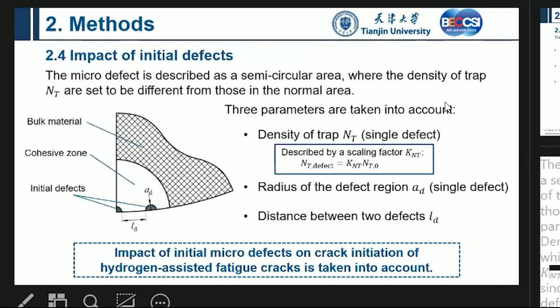I would like to introduce some defects because, for example, the material is not normal. So micro defects will be described as a semicircular area, whereas the density of hydrogen traps, NT, will be set different from the normal area. For example, we would like the defect to have KNT multiplied by NT0. Okay, this is our idea, just like replacing something.